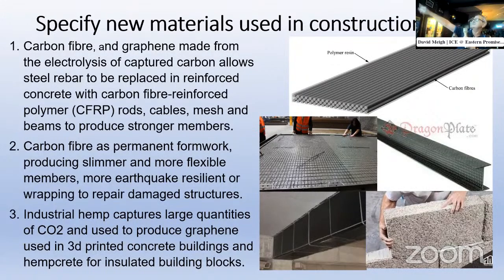On the right hand side you can see a beam made of carbon fiber instead of a steel beam. In the center here there's a picture of carbon fiber mesh made for thin panels and floor slabs. And I'll show you something made from these a bit in the next slide. For existing structures that perhaps have started to age and start to crack, we can reinforce them with carbon fiber CFRP panels. And then on the right-hand side is a picture of what's called hempcrete, industrial hempcrete, which